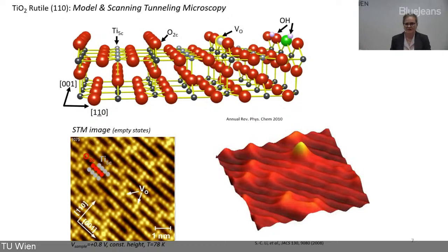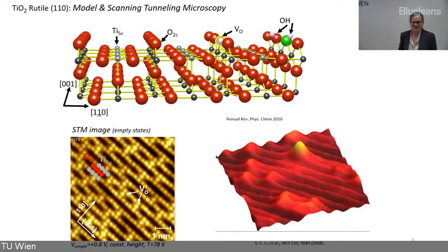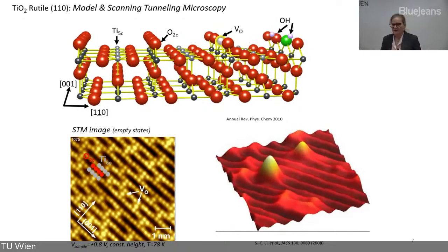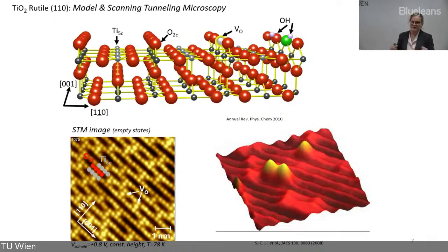What I want to show you next is an STM image again, in a little bit more fancy 3D representation, and this big thing that looks like a mountain is actually an OH group, the one surface hydroxyl. I want to put your attention to this region where this arrow points. I will now play a very short movie where a water molecule comes, adsorbs at the surface, dissociates, puts the proton to the next oxygen, and then the two diffuse away. So here, a water molecule comes, dissociates, you make two hydroxyls, and then they move apart.